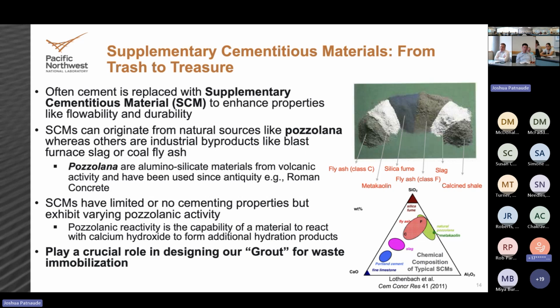So the technical term for these are supplementary cementitious materials, things that aren't cement that we add in to grouts or cementitious materials to make our final products. These supplementary cementitious materials can have different sources. They can come from natural sources, which we would call pozzolana, which means a naturally occurring material that has pozzolanic activity. Pozzolanic activity is the ability to react with water and a bit of calcium to produce those hydration reactions. And these are mainly aluminosilicate materials that come from volcanoes or from prior volcanic activity, which in its fundamental sense, you have a mineral that contains calcium and silicon and aluminum, got exposed to very high temperature, gets powdered down, becomes reactive with water. It's no different than what happened with that cement, where you took limestone and clay, cooked it at a very high temperature, produced a powder that can react.